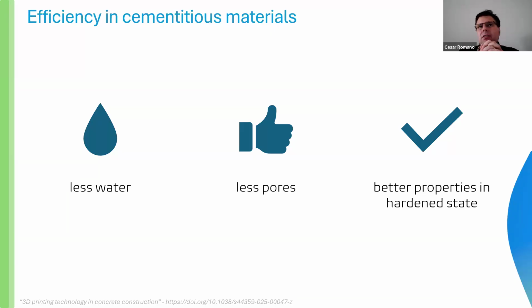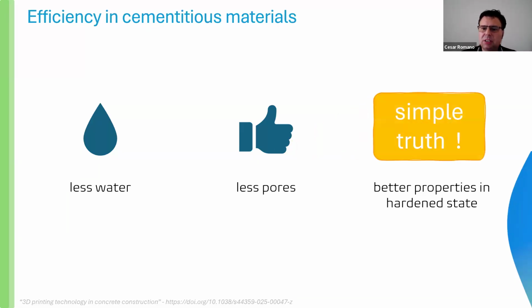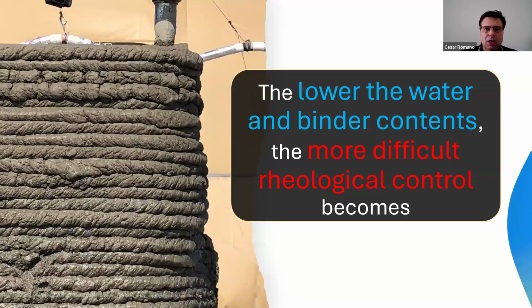If you reduce the amount of water that you use to mix the composition, you will have less volume of pores in the microstructure. And in consequence of that, we will have better properties in the hardened state. For sure, this is true. But when we reduce the amount of water and the binder content, the rheological control becomes more difficult. So this is where the rheological characterization is most useful.